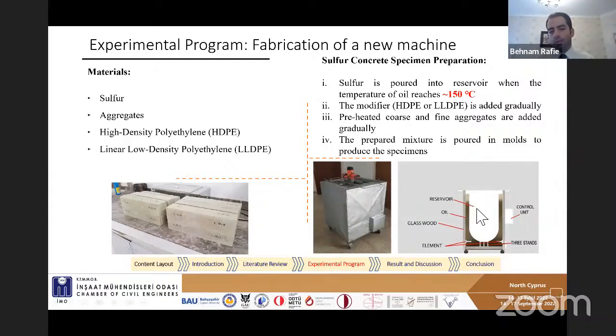This mixer has 2 reservoirs, and inside we mix our material, and initially we heat the oil up to 150 centigrade, and then add sulfur to melt it. Then, in this study, we used high density polyethylene and linear low density polyethylene to modify our concrete. So we used sulfur, aggregates and these 2 modifiers. I should also add that we preheated our aggregates up to 180 centigrade in order to save our time heating the aggregates inside the mixer.